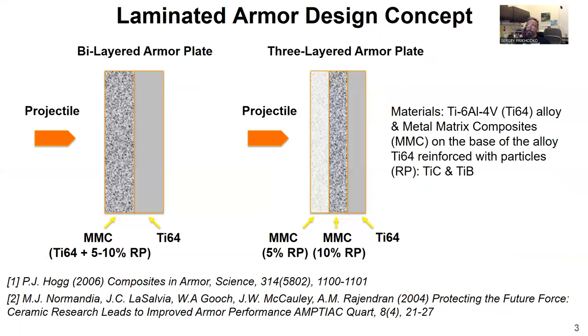Required combination of armor properties can be obtained in layered structures that combine at least two different materials with different properties. Conventional engineering materials such as metals absorb mechanical energy by plastic deformation. Composites or ceramics, on the other hand, absorb energy by fragmentation. For the back layer, we suggest using ductile alloy Ti-6Al-4V, and for the front layer we suggest using composites, metal matrix composites on the base of this alloy reinforced with hard particles of titanium carbide or titanium boride.